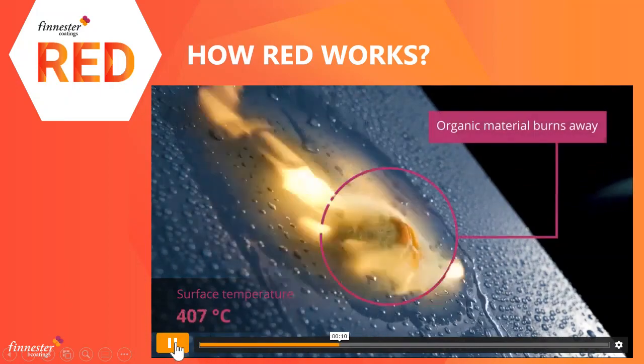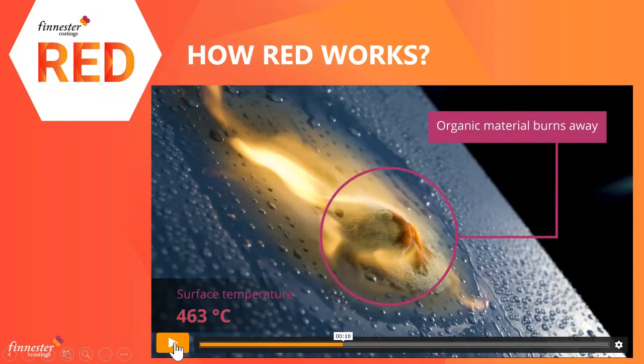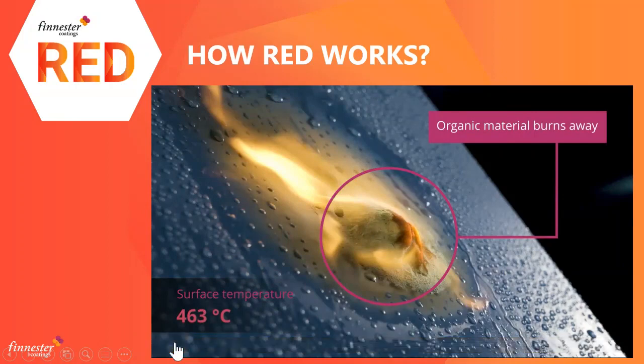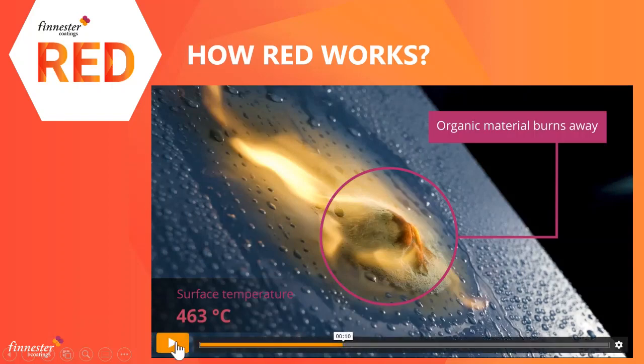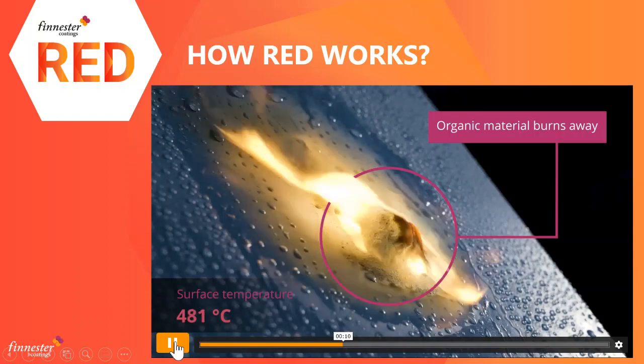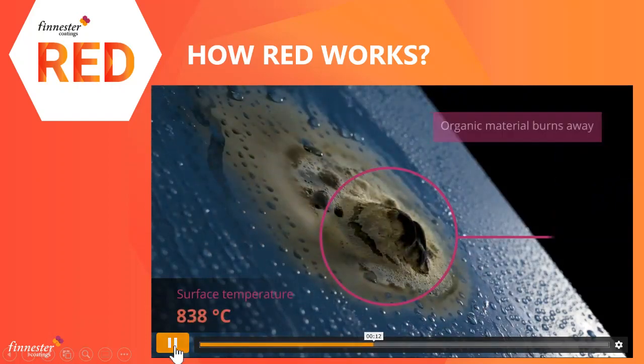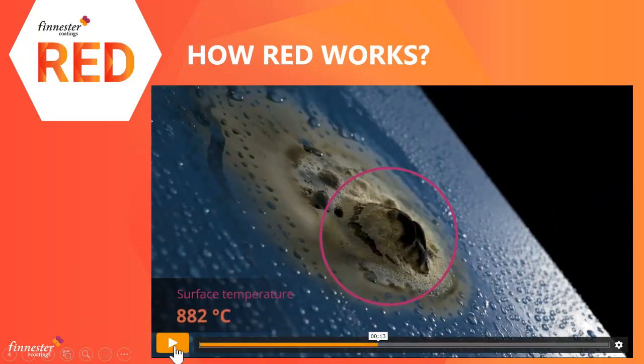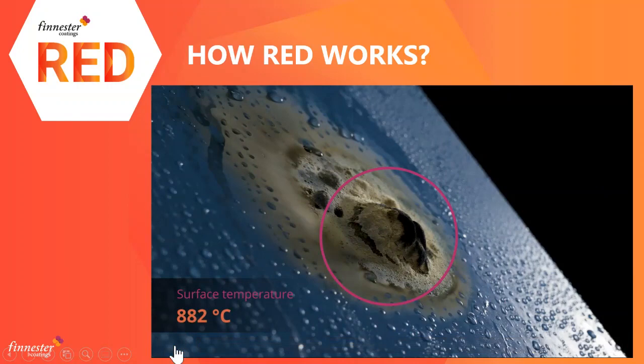The Bunsen burner comes, and what happens next is, because it's an inorganic-organic system, the organic material burns away, and that's completely fine. There's a small peak that the heat is generating, but that burns away in those temperatures, 300, 400, 500. But when you continue burning, then all organics are gone, and the rest of the inorganic and the hybrid red has turned to the ceramic